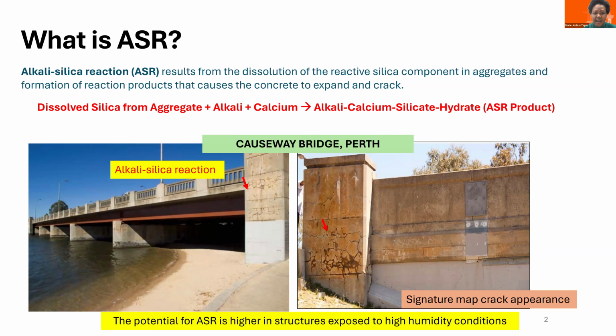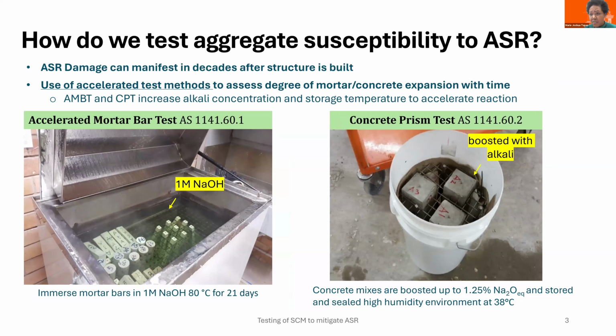The dissolved silica in the concrete then starts to interact with other ions present, such as calcium, forming a product we know as alkali calcium silicate hydrate. Now, this ASR product, once it accumulates, has a tendency to result in concrete cracking. Once concrete cracks, it becomes prone to other deterioration mechanisms. ASR preferentially happens in locations that are very close to water, and therefore susceptible structures are bridges, dams, as well as marine structures.